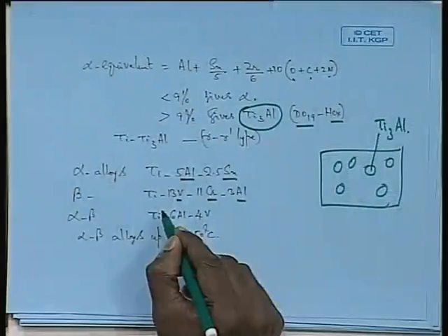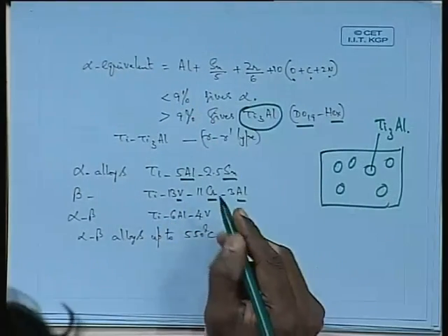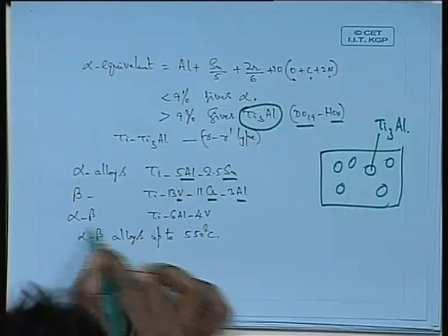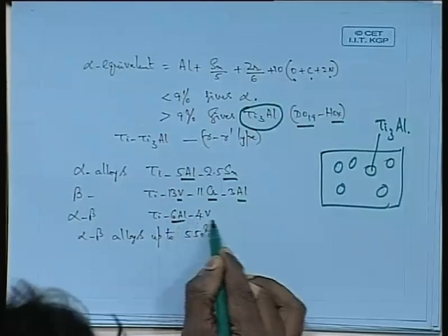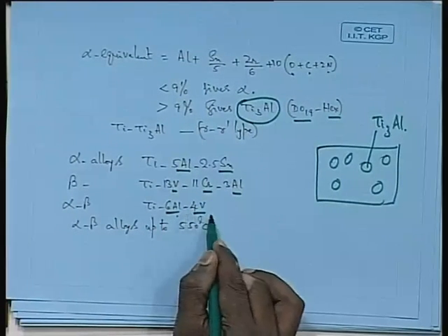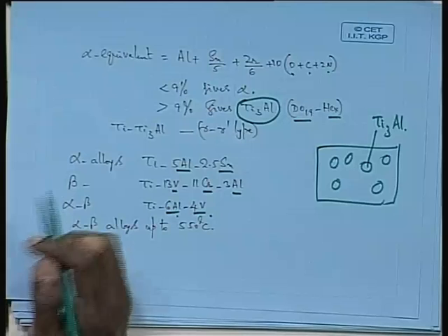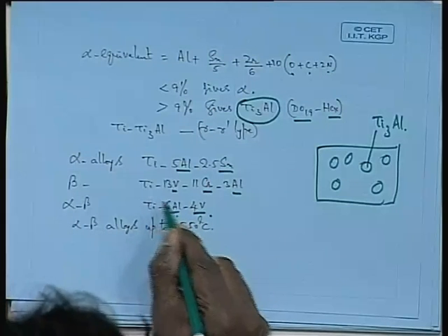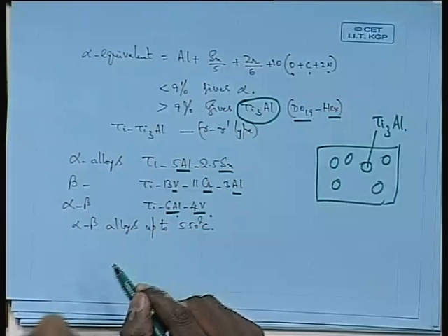So these are the alloys for high temperature applications and at the same time less density, whereas the beta alloys, because we are adding elements which have high densities, the overall alloy becomes dense. Then we can have alpha beta alloys where you can have a combination of alpha stabilizer and beta stabilizer. The most popular alloy is titanium 6 aluminum 4 vanadium,